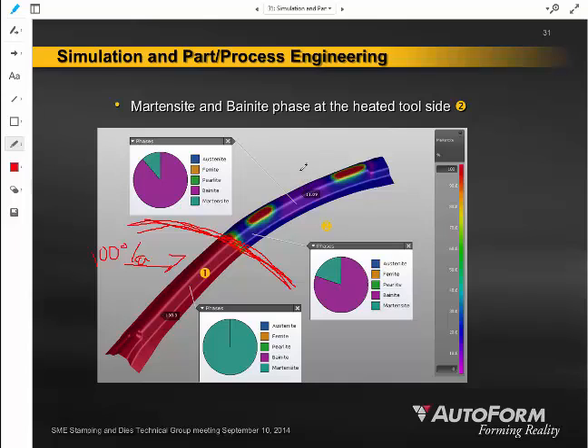But you can also notice that there's lower percentages of martensite. In this purple area, we're seeing martensite levels as low as 10%. So that material is going to be more like the original strength of the steel directly from the stamping mill, the coil mill. It's not going to have that value-added quenching characteristic of being increased in strength.